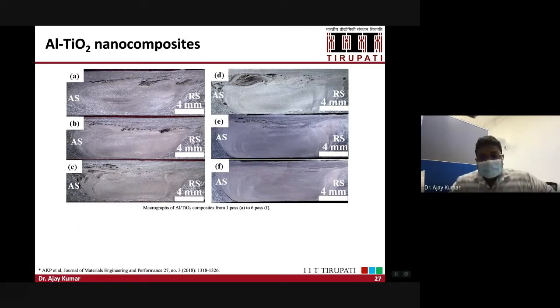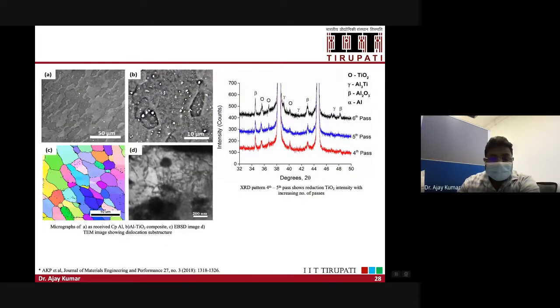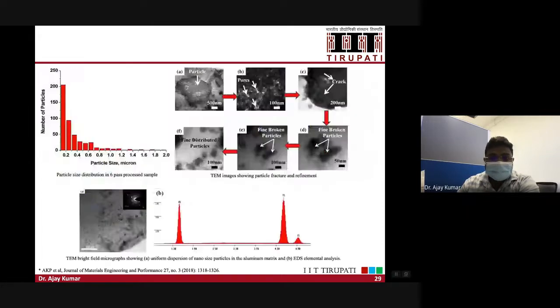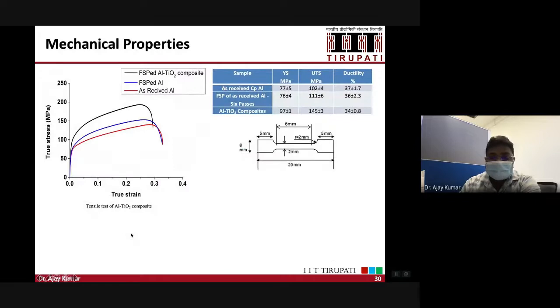Then we did a similar type of study in aluminum titania composites. Here also we have demonstrated the distribution of titania particles in the aluminum matrix and how these particles are getting fractured during the process. So you have the bigger particle which is porous, and by the multi-pass process these particles are fractured and they go to the nanoscale range.